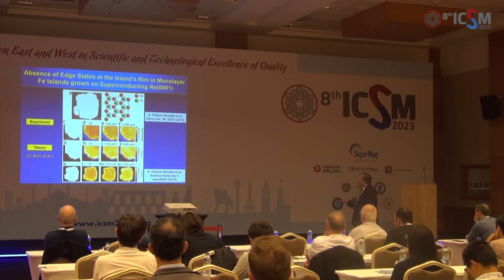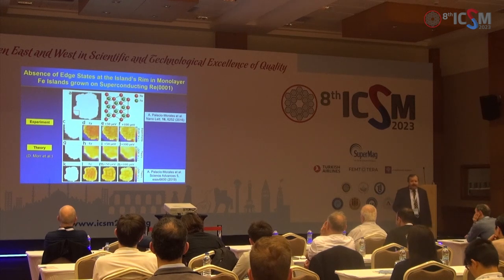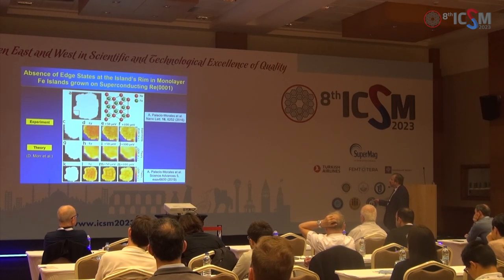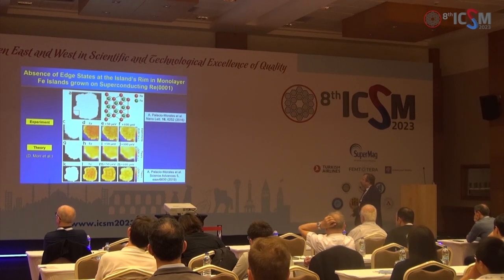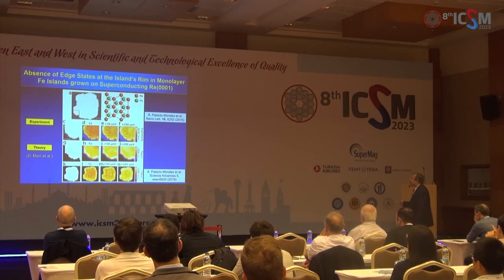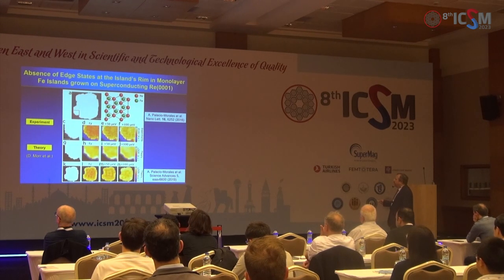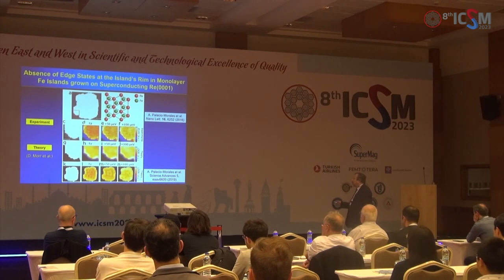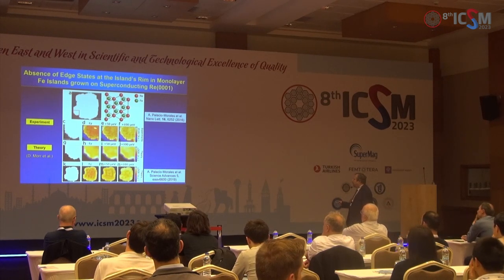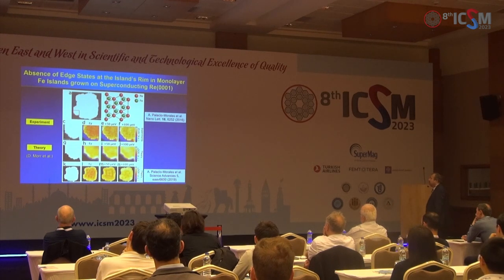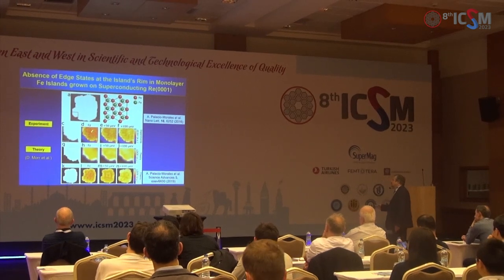If we zoom into this scanning tunneling microscopy image—the right tool for atomic-scale structures—we see the island edge enlarged. With the STM as a spectroscopic tool, we record the differential tunneling conductance spatially resolved, which gives us a measure of the local electronic density of states as a function of energy, in this case at the Fermi level.